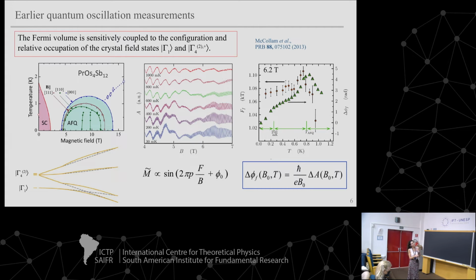And what we saw in this earlier work was, this is the axis that you care about, and the green triangle. So this is phase as a function of temperature. If we start here at high temperature, we see that the phase is increasing. Then it hits a maximum, which is at this temperature, 6.2 Tesla, so it's around about here. So this maximum corresponds to the phase boundary here. And then the phase decreases inside of this phase. And then we noticed at 250 millikelvin or so, this was the unusual part, that the temperature dependence became much steeper and much more pronounced. So this is not at all what you would expect. You would expect that this should just saturate here.